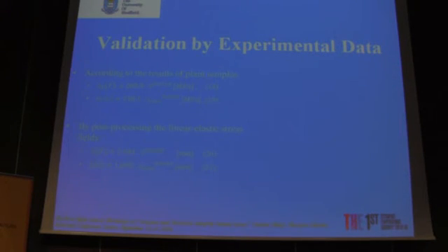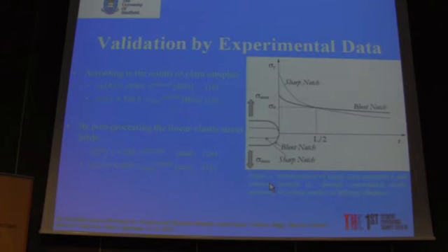Once our initial assumption was confirmed, according to the results of the plain sample, we get the equation for the power law of the dynamic failure stress for the plain sample. By post-processing the linear elastic stress field with the same strategy as shown in Figure 2, we can simply get the trend of the critical distance L, which is a power law as well, as equations 20 and 21 show, against the loading or strain rate.